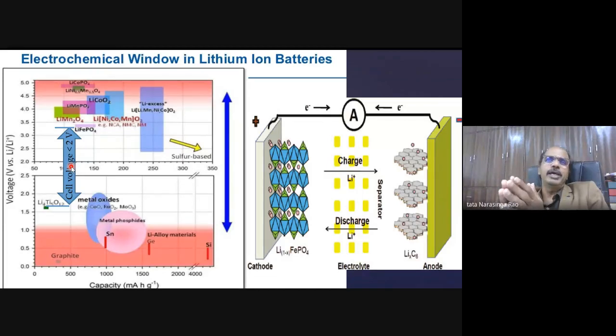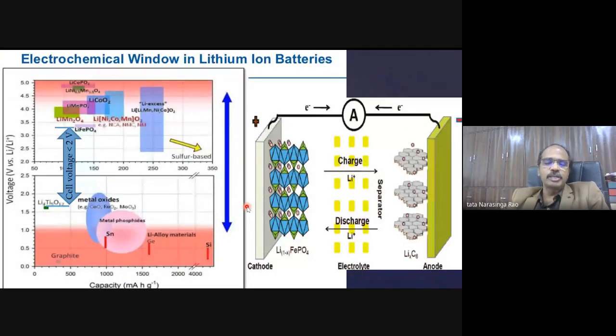We want to make in India, where the public transport system is so widely used, so that's why even Toyota and Suzuki are all looking for LTO batteries as well. To make those batteries, the starting materials are lithium iron phosphate and lithium titanate, these two key materials, knowing that India needs these materials. Of course, lithium nickel cobalt manganese oxide has slightly higher voltage. Some high-end cars like Tesla use lithium nickel manganese cobalt oxide because it's a higher voltage. But the problem here is the cost because cobalt is involved, and there is an issue of stability. But you can manipulate it by putting in more money. So the Tesla car is so expensive.